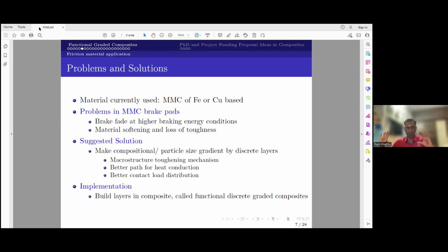When I show the images, you'll be able to understand what I mean. And when I introduce the particle size and the composition gradient, I can create a better path for heat conduction. If I have only a composite, the conductivity is poor. If I have a metal with the composites, better conductivity will be ensured. And by having this particle size gradient, I can ensure better contact load distribution. Whatever brake pressure I apply will be uniformly distributed across my brake pads. So this is the fundamental idea we thought.